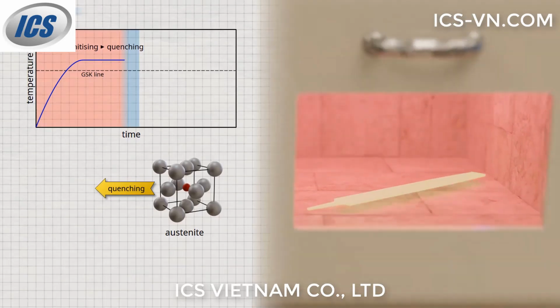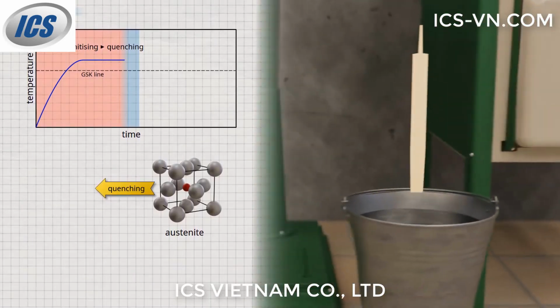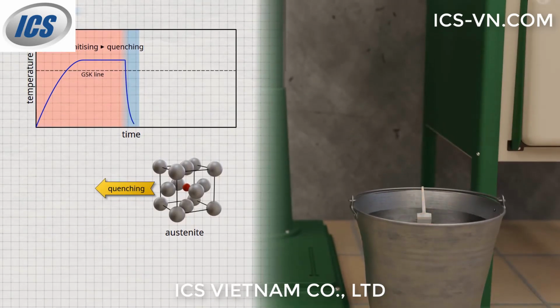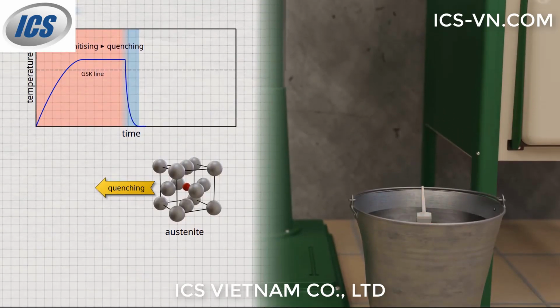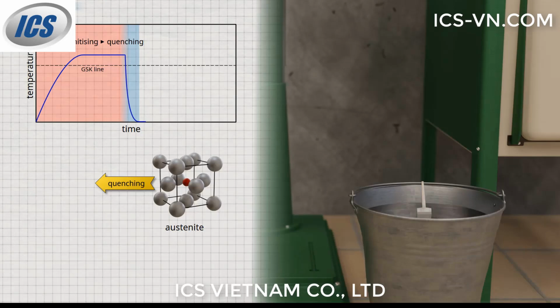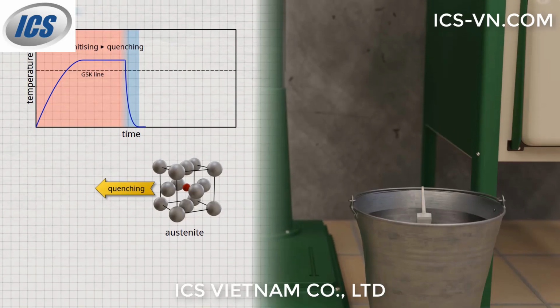Quenching can be achieved, for example, by immersing the workpiece in water or oil. During quenching, the carbon remains forcibly dissolved in the forming martensite lattice despite the lattice transformation.